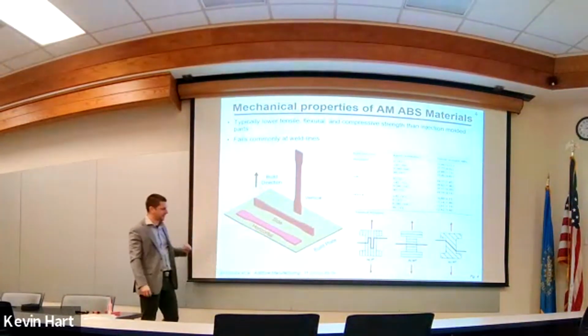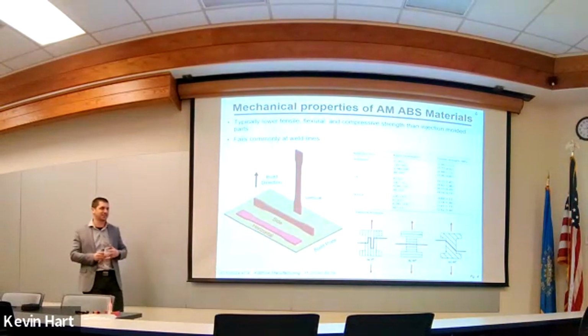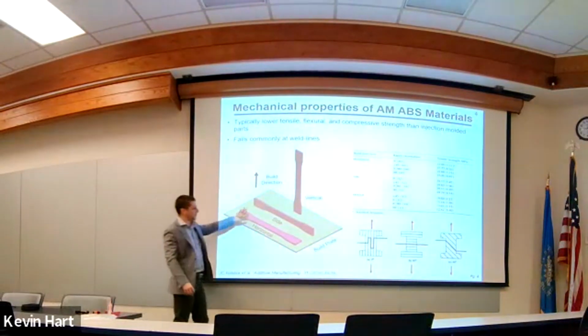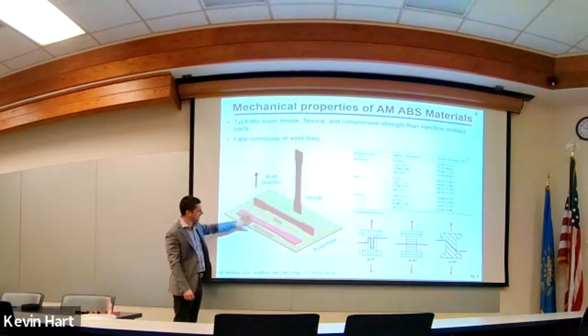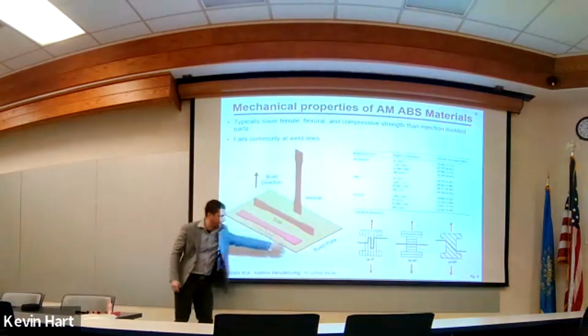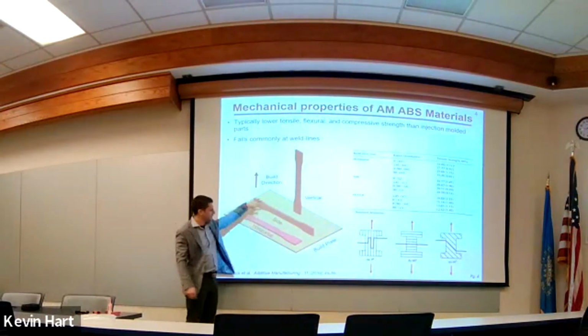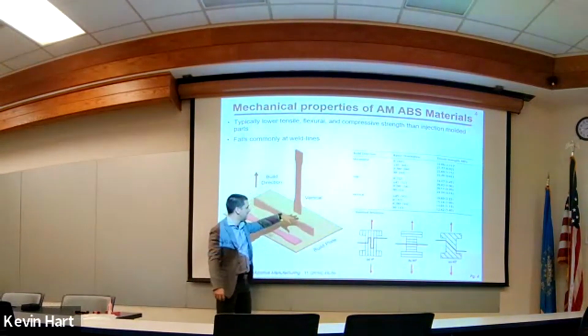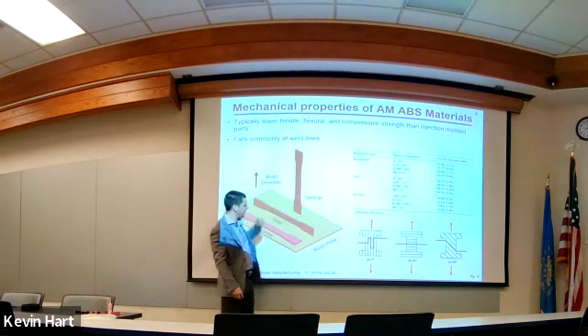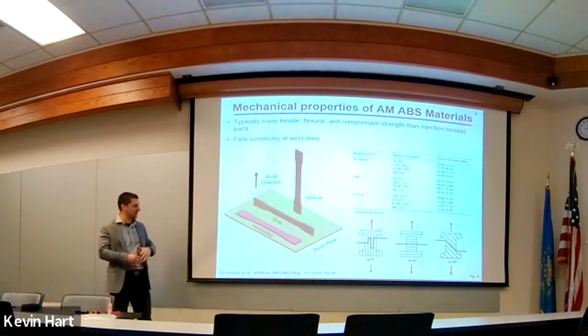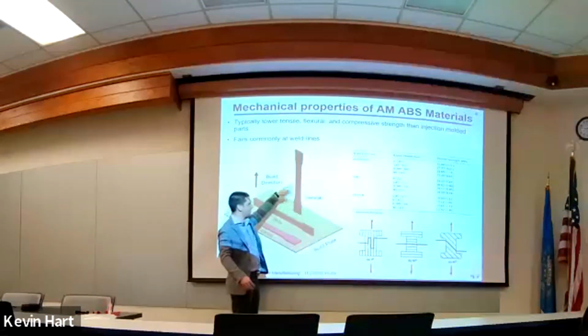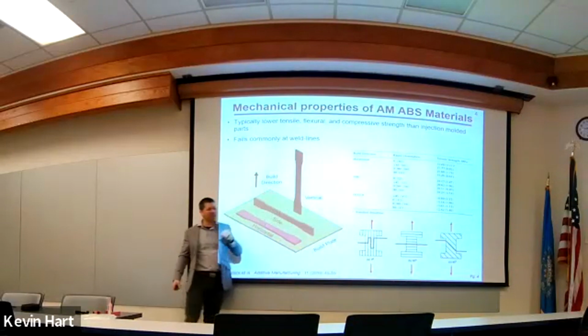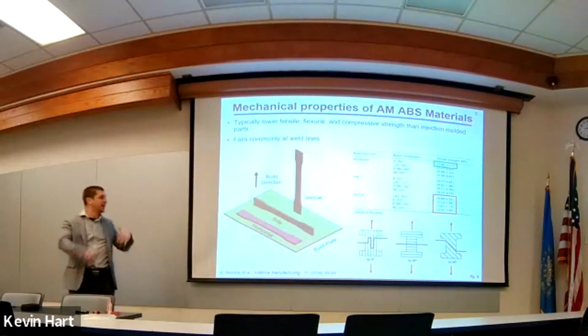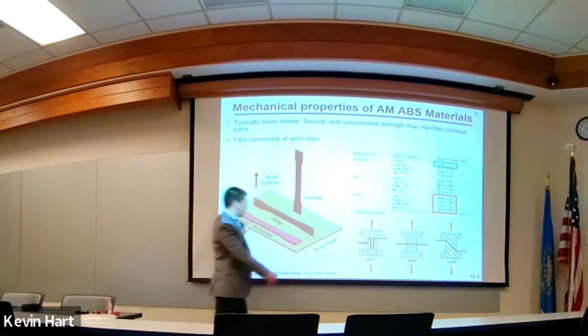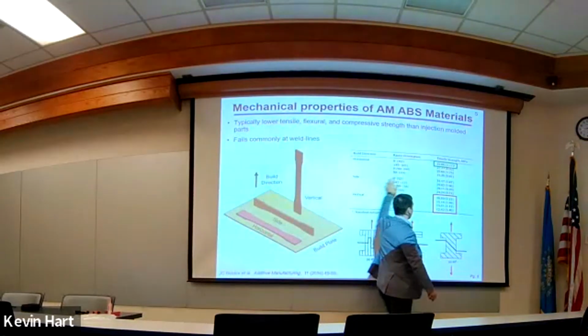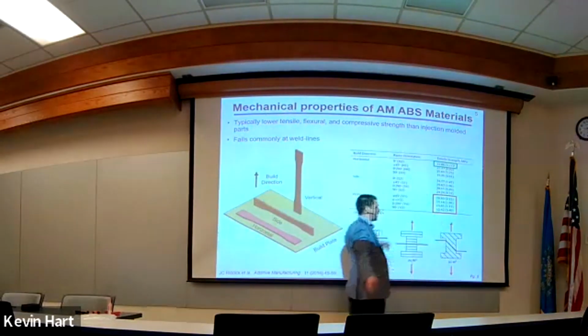Okay, you can put some numbers to this by making dog bones of your own. There's an author that did this in 2016, and I like his data because he did a lot of cool stuff, where he made dog bones that were oriented in 3 different orientations. A horizontal, so the raster is going this way, sort of the side profile, and then a vertical profile. And in this situation, you'd expect the vertical to tend to be the weakest because that's where the stacking or the layering is occurring. So if you're loading across that layering, you'd expect quite a bit of weakness. And if you're making a dog bone and it's laying on its side, this horizontal orientation, you get a tensile strength.